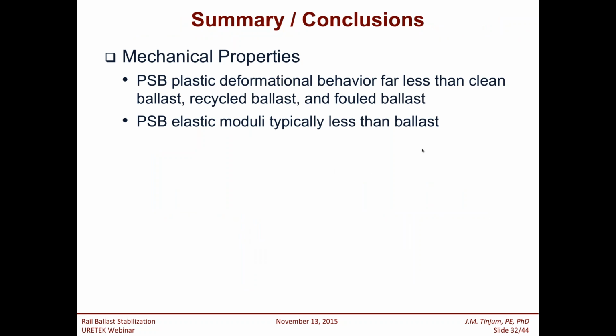polyurethane stabilized ballast, as measured by plastic deformational behavior, is better controlled than clean ballast, recycled ballast, and definitely fouled ballast. We can stabilize fouled ballast depending on the type of material that it's fouled with. And even though polyurethane stabilized ballast has an elastic modulus that's typically less than ballast, that just means that recoverable, or elastic, strain does occur in the material, but the cumulative plastic strain does not manifest. So that's actually a good thing as far as a property.